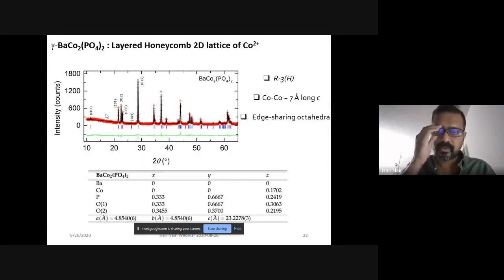Once we get a crystal, we study its structure with X-ray diffraction and analysis using what is known as the Rietveld refinement method, and confirm the space group. So that's what we did. We index each of these peaks, and that corresponds to special occupation of crystallographic positions by the atoms. And we could verify that the compound actually crystallizes in R3 bar, the hexagonal structure, which is the honeycomb structure.